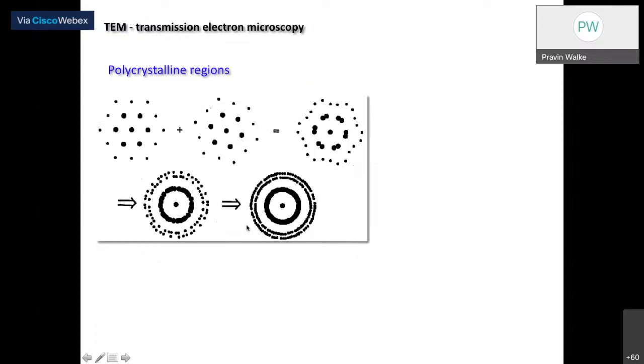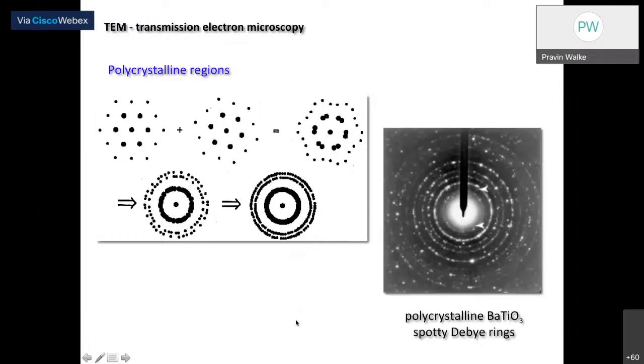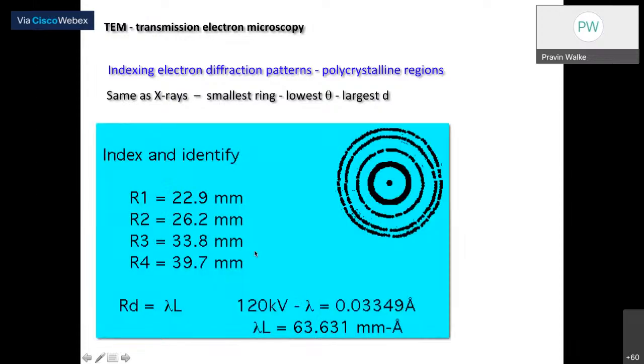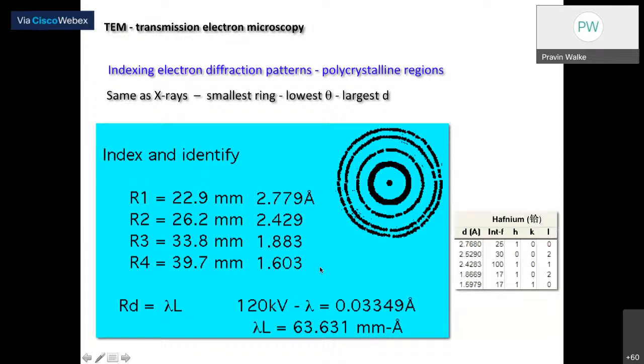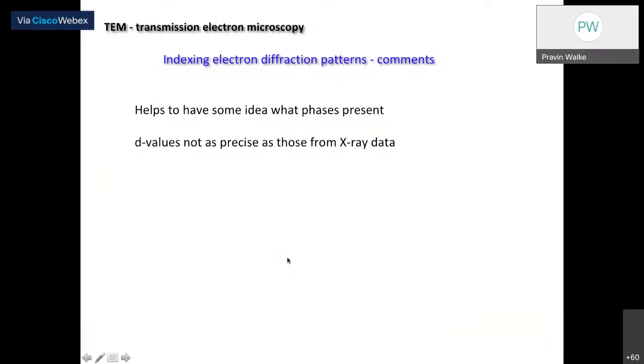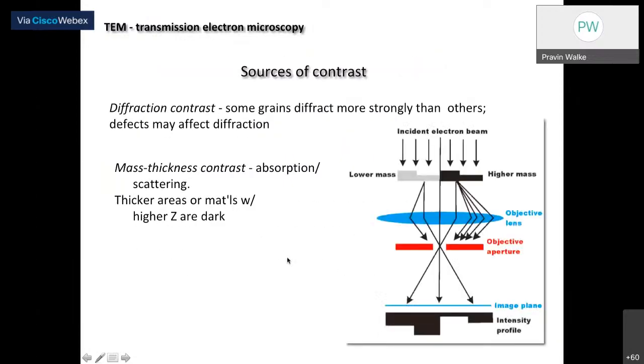right? Here it is polycrystalline. Why polycrystalline? Because there are various crystals. One crystal is in this form, another crystal in this form. So multiple crystals together can generate this kind of ring structure, right? We have already seen that in one of our MnO2 samples. So in these ring structures, usually we know the distance between the rings. The larger ring will have the higher resolution, and the lower ring will have the lower. So this is a clear indication of this. And from this d value, we can easily index the plane of these individual rings. So this is how we can do the indexing.